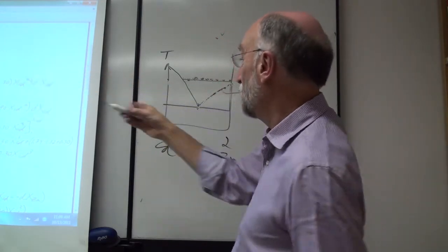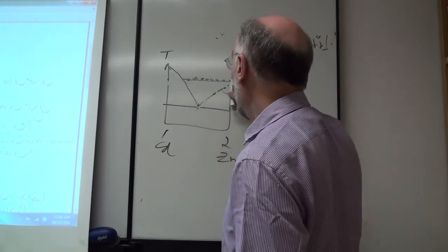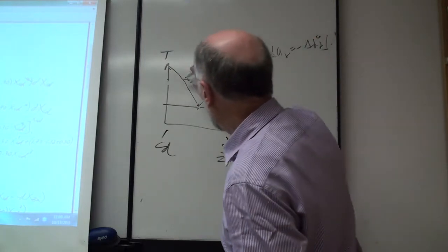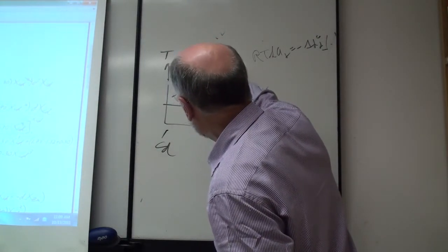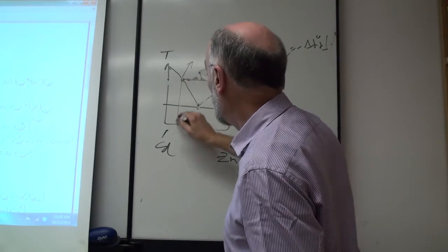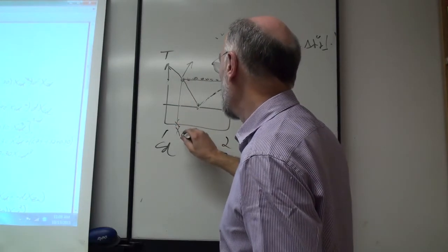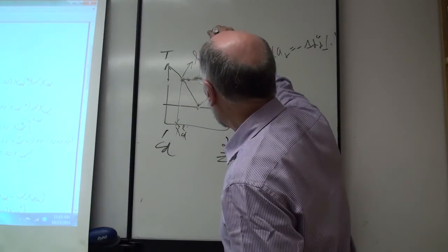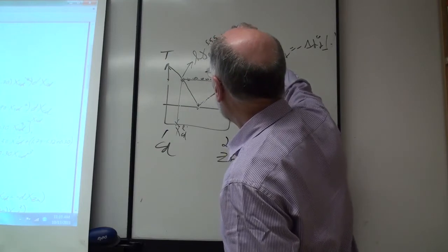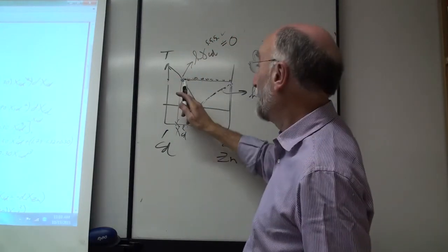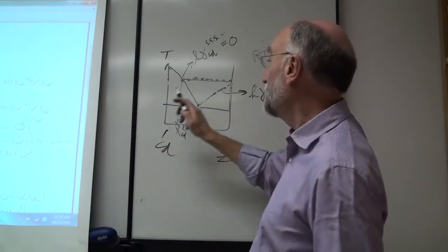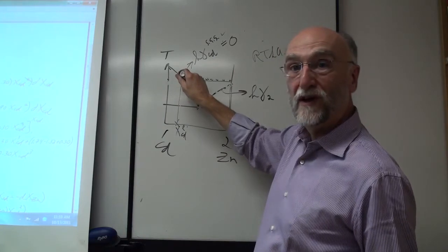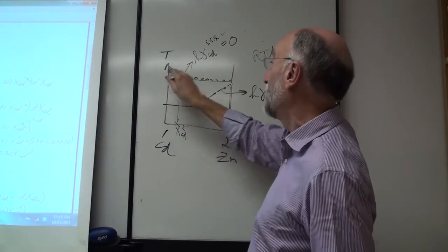Now I can integrate the Gibbs-Duhem equation to get log gamma cadmium over that composition region, give or take a constant of integration. But now I know that at this point I can use this composition. If the liquidus composition is known, this is X cadmium on the liquidus, I know that log gamma cadmium, at least with respect to the solid standard state, equals 0. So I can integrate the Gibbs-Duhem equation to get the activity coefficient of cadmium over this region using the one known endpoint value here, because I know that on the liquidus it's in equilibrium with solid cadmium.